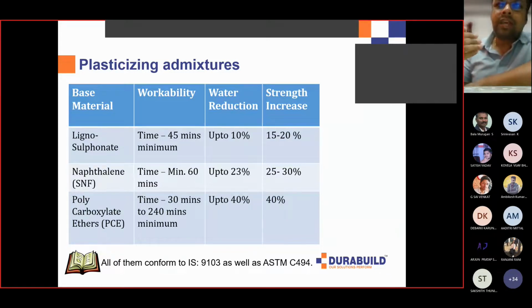Then, science improved, chemistry improved. Then we got something called naphthalene, SNF based admixtures. Now, SNF based admixtures cause water reduction as high as 23%. So you can imagine there is much more water reduction, which would mean the strength increase will also be much more. And finally, polycarboxylate ethers. These are the latest third generation, or you can say fourth generation admixtures, which are giving you water reduction as high as 40% and also giving you strength increase, because obviously if the water comes down, the water cement ratio will also go down and the strength will go up.